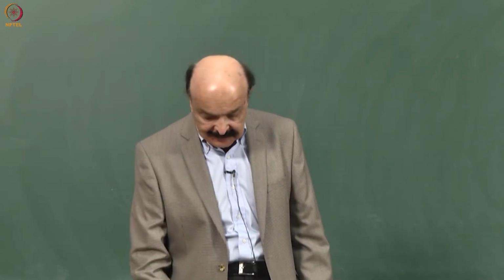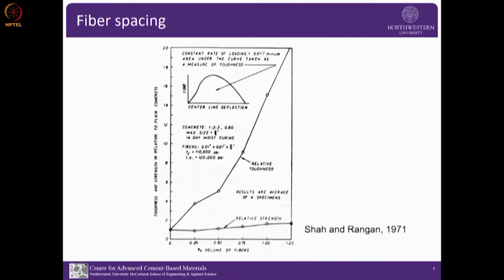Then that got started, and we did some work with randomly distributed steel fibers. Here you can see the percentage of fibers, and of course with more volume of fibers they will be more closely spaced, versus tensile strength, and then what we call toughness, which is the area under the load deflection curve. This was the work I did with Vijay Rangan, who is now retired from Perth. You look at it and see there is really no increase in tensile strength, but there is a substantial increase in toughness.